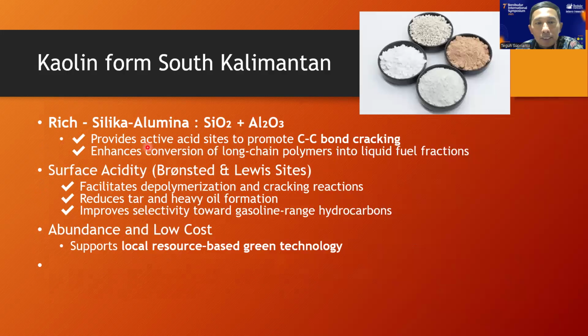This provides active acid sites to promote C-C bond cracking, enhancing conversion of long-chain polymers into liquid fuel fractions. The surface acidity facilitates depolymerization and cracking reactions, reduces tar and heavy oil formation, and improves selectivity toward gasoline-range hydrocarbons. And of course, in our area in South Kalimantan, it is abundant and low cost, and at this time its value is still low.